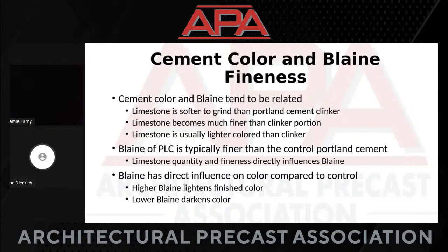As we look at the cement color and the Blaine, they tend to, in my opinion, coincide together. And I'm approaching this more from a white cement supplier point of view, but this will impact, as Jamie mentioned, white or gray. The cement color oftentimes does lighten up a little bit when you're adding PLC, or limestone, to make it a PLC cement. The Blaine tends to increase. That's not always the case. It's going to go by plant to plant, but typically when you add that limestone, because it is softer than clinker, in a finish mill, the fineness does tend to increase.